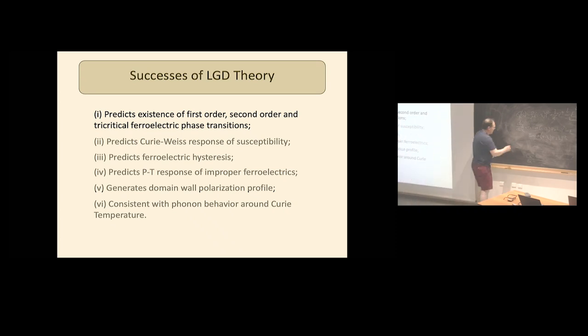All right, susceptibility. I used to, I'm not even joking, I used to lie awake at nights worrying about susceptibility. And in the end, I found out that it was just how susceptible a system was. So the susceptibility here, if you apply an electric field, is how much polarization you develop for that electric field, how susceptible the system is to developing polarization under the application of an electric field. Formally, susceptibility is the change in polarization with respect to the field. Now this is tricky. We have an expression that's explicit for field and implicit for polarization.